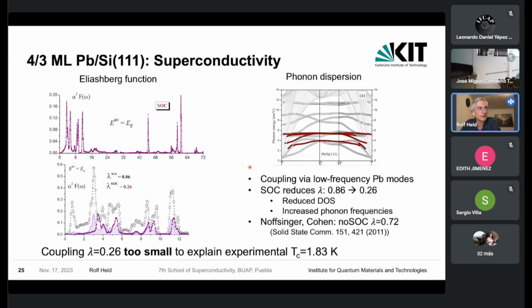We have then performed the same machinery as before and finally calculated the Eliashberg function, which is shown here. And you see that there are certain contributions and certain peaks coming from certain phonon modes at lower energy, and also some high frequency modes which are due to the silicon vibrations. Here is shown the phonon dispersion, where you see certain flat bands, which are all due to the lead atoms lying on top of this silicon surface, and the silicon vibrations are shown here by this gray background, which reach much higher frequencies.